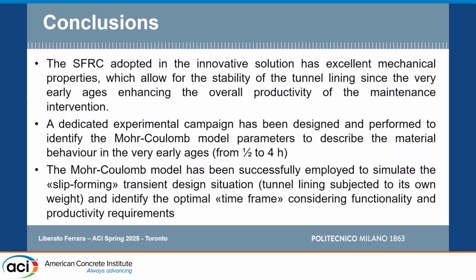As a matter of fact, when concrete transitions from fluid to solid state, there is this gray zone where we apply the Mohr-Coulomb criterion to model the behavior of concrete, and we performed a dedicated experimental investigation to identify and calibrate the model parameters. And we were able to find a reasonable solution for the demolding or the slip forming of our tunnel, which complies with safety requirements, integrity of the structures, and productivity of the technology as well.